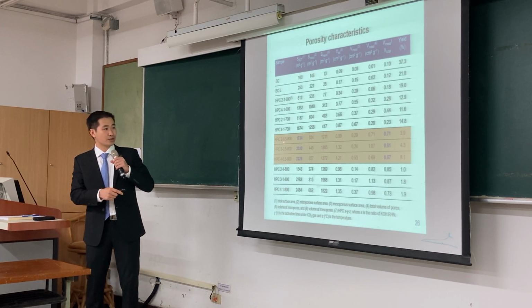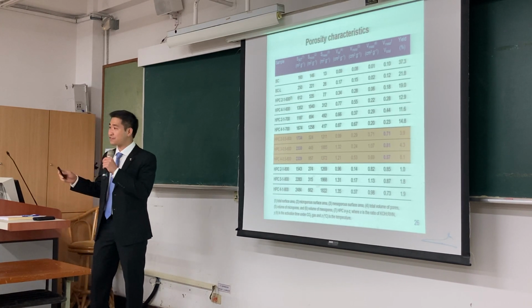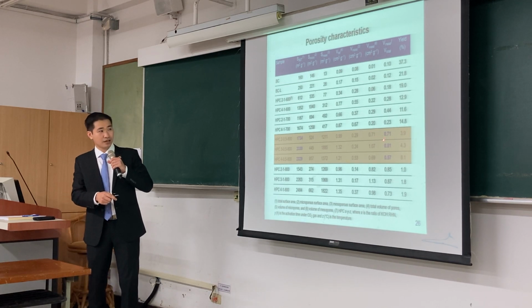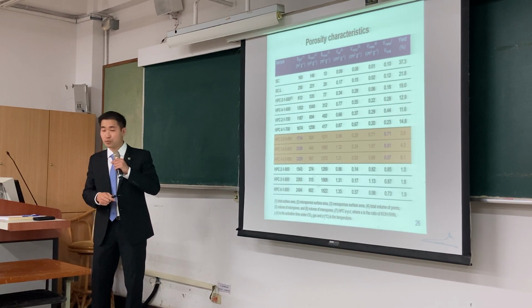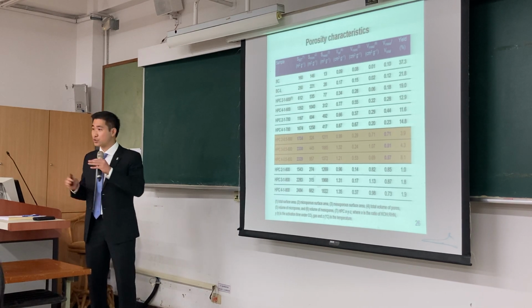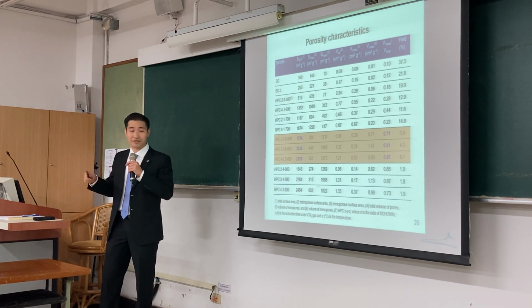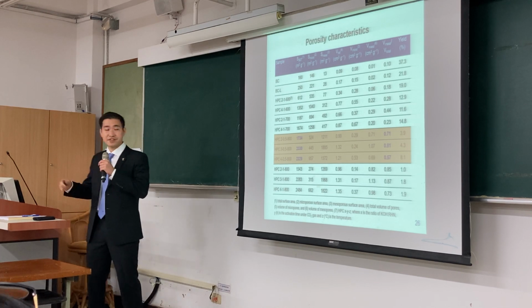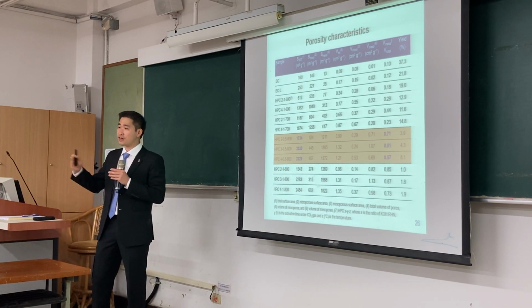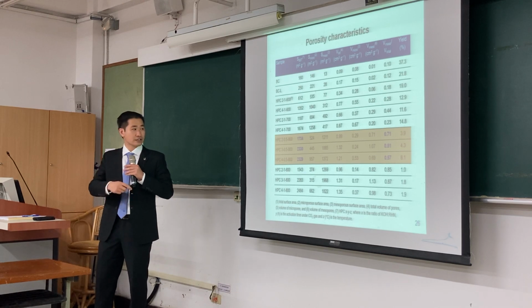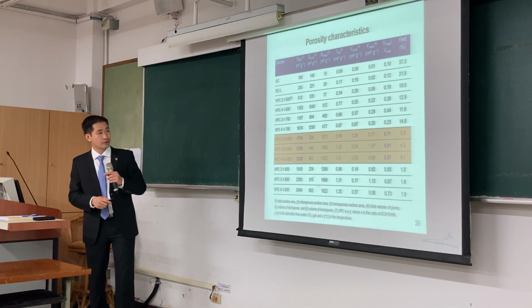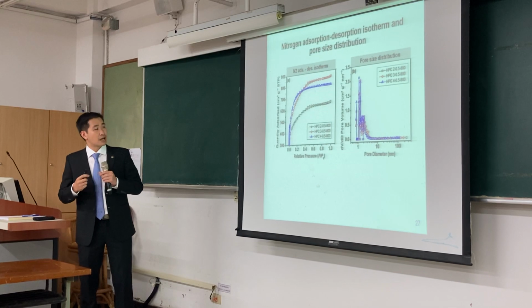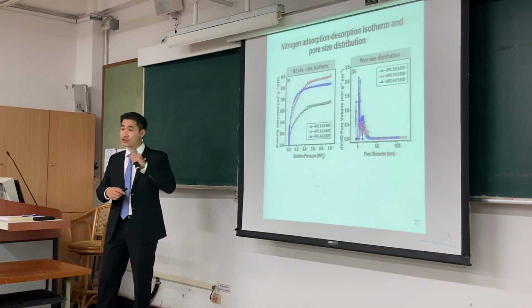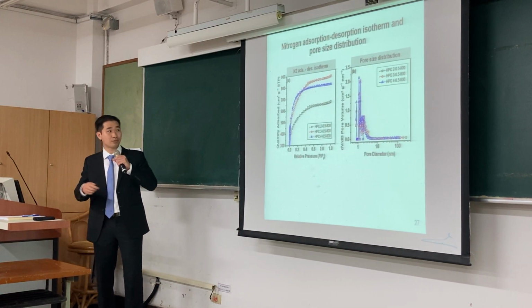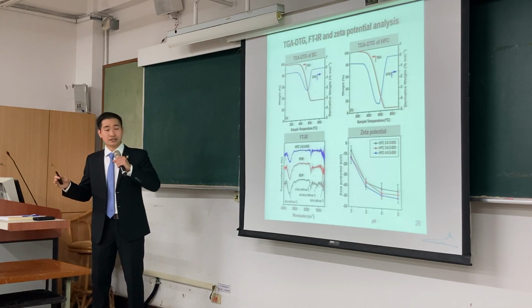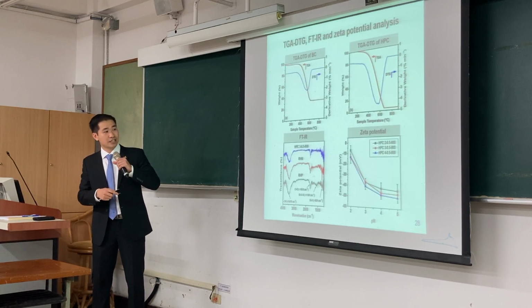Notably, HPC2 and HPC3 0.5 800 have nearly similar mesoporosity, while HPC4 0.5 800 had nearly similar specific surface area. So for further investigation, I collected these 3 samples. The nitrogen adsorption, desorption isotherm, and pore size distribution of these 3 samples are shown here. The characterization of the HPC samples is shown here.